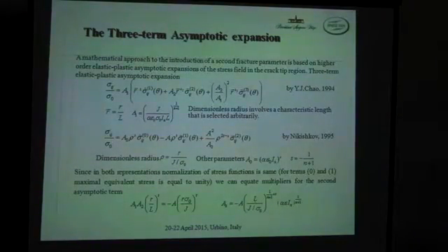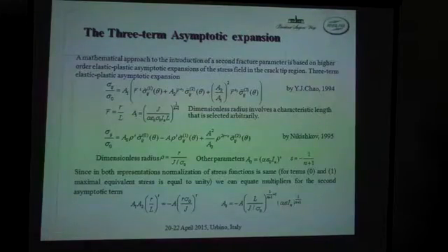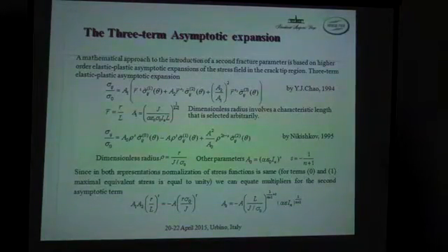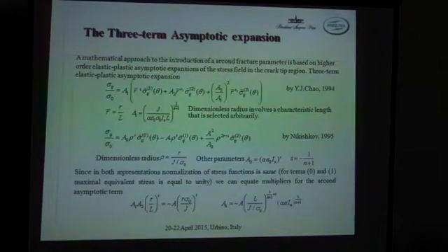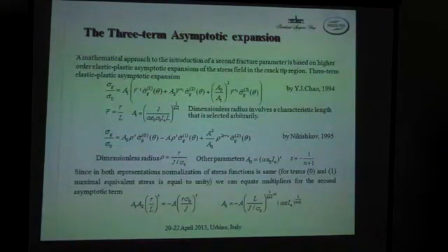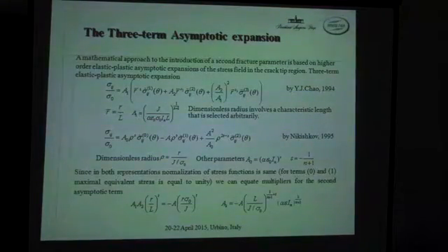The difference is just in the determination of the distance from the crack tip. And it should be possible to show that there is a connection between all parameters of these equations. Of course, if we are talking about elastic-plastic fracture mechanics, these equations contain some parameters which reflect plastic behavior, for example, based on the Ramberg-Osgood law, and n is the strain hardening exponent of the diagram.